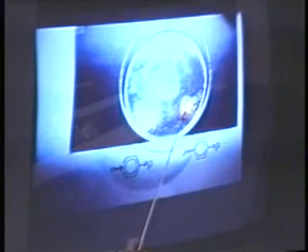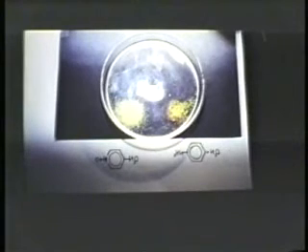Now, you don't even have to grind some of these samples. What I have here, although the structures are backwards, in the Petri dish on the left is paranitropyridine N-oxide. And on the right, I have paranitroaniline, which is yellow. And around the edges, you can see something that's red. The red color develops in this Petri dish if you simply cover it and let it sit on the benchtop for a while. And what happens is that paranitropyridine N-oxide, which has a reasonable vapor pressure, simply sublimes and finds its way over to the paranitroaniline, and when it does so, co-crystals form.